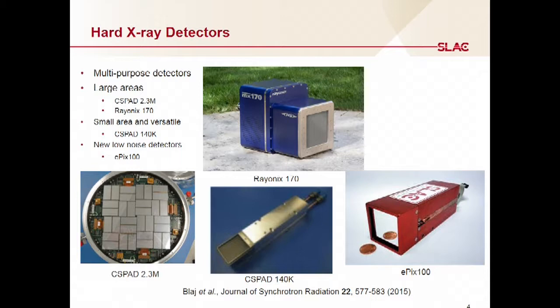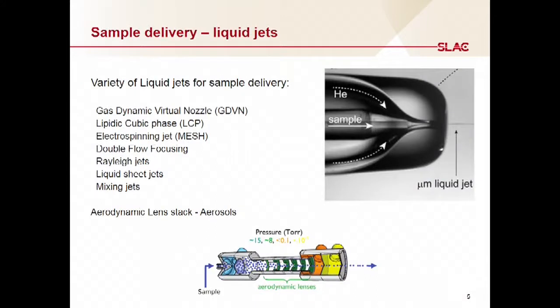There's also a series of smaller detectors. The CSPAD 140K, which is one 2x2 of the full CSPAD. And also the ePix 100, which can be used as small detectors for spectroscopy, or if you want to go high angle and you have some high angle scattering you want to see. All of these three are relatively low noise, which is very important if you have very low signal, which a lot of spectroscopy signals are. Most of these detectors can be incorporated at any of the instruments. You just have to figure out what geometry you want and what science case you actually need, but those things are typically readily available anywhere.